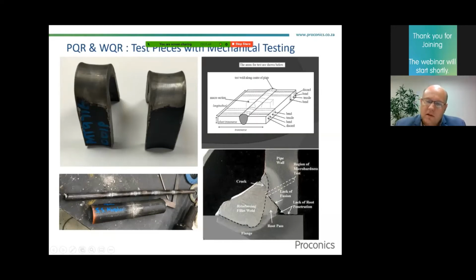Then on your bottom right, these are possible defects that can arise on a fillet weld. As you can see, there's a pipe welded to a flange by means of a reinforced weld. It also has a partial penetration root weld. The defects that arose here were a lack of penetration in the root, also a lack of sidewall fusion in the root that initiated into a crack of the reinforced weld. Also, you'll observe the area where micro hardness test values will be taken.